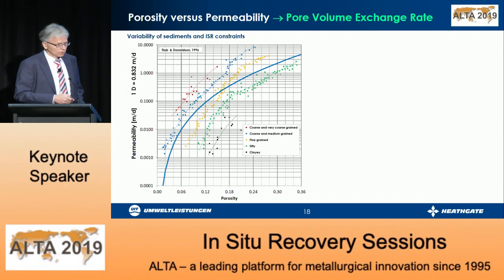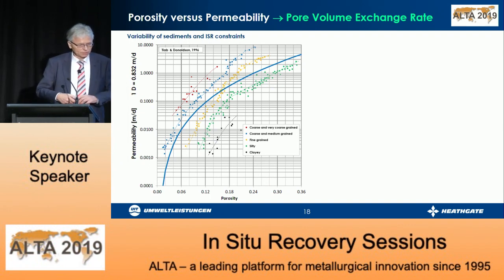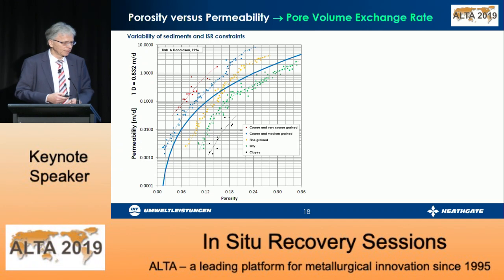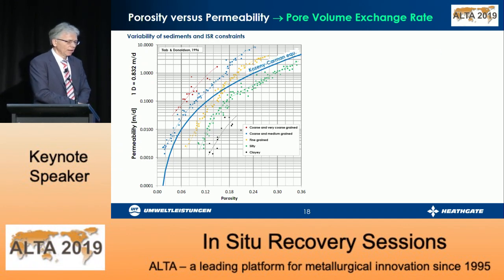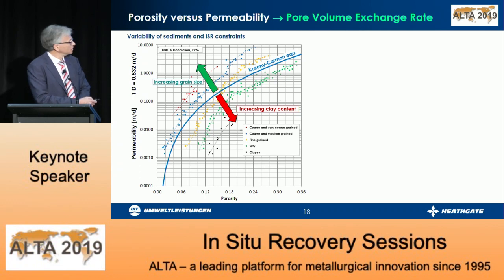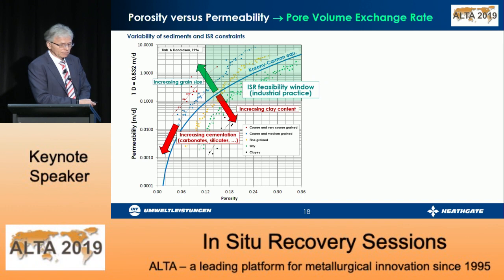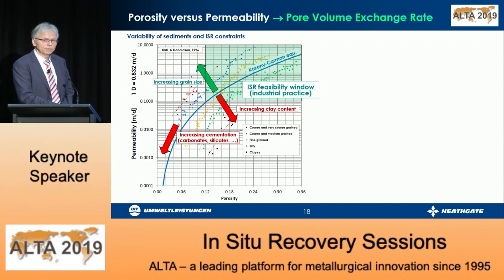Here is a summary of a relationship based on data. Correlation of the free fluid porosity and the permeability. These are the overall trends. The guideline is based on a Kozeny-Carman equation, and here you see the trends. On the one side, increasing grain size results in a better permeability, and an increased clay content results in a lower permeability. What we consider as the window for applying the in situ recovery is highlighted here by this green area. You need porosity, you need permeability to establish a reasonable wellfield operation.